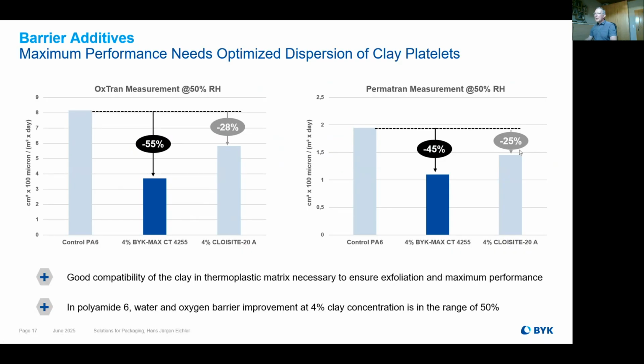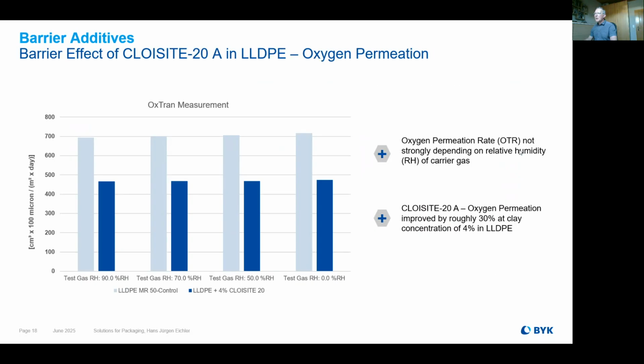So that means a good dispersion of clay will really improve the barrier properties, and it's really important to take the right clay into your polymer system. If we check now as another example the Cloisite 20A, you remember that was still not performing so well in the polyamide 6, but here in the LDPE, you see with the oxygen permeation, it's really nicely improving in that way.